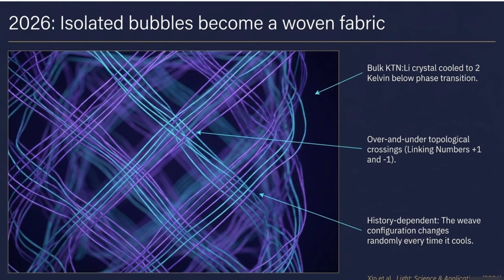Right. And to prove that this was a highly specific mechanism and not just the laser heating up the crystal, the researchers tried scanning the fabric with a 1040 nanometer infrared pump laser. Right. And the infrared light has a longer wavelength and lower energy, so it just didn't have enough juice to kick the electrons over the band gap. The fabric ignored it completely. It only responded to the specific wavelength of the green light.